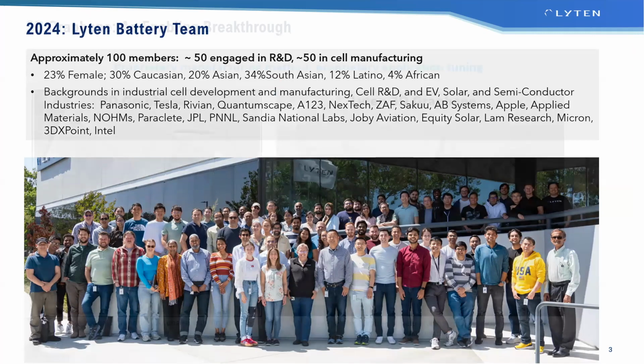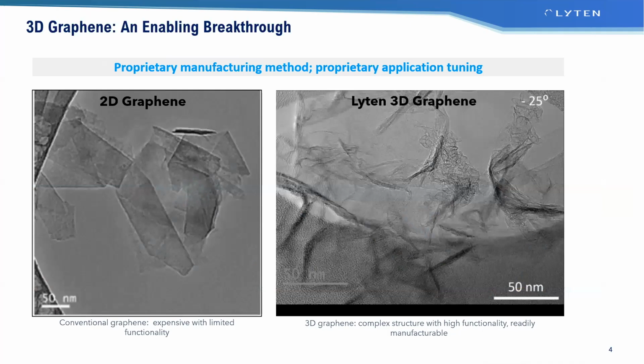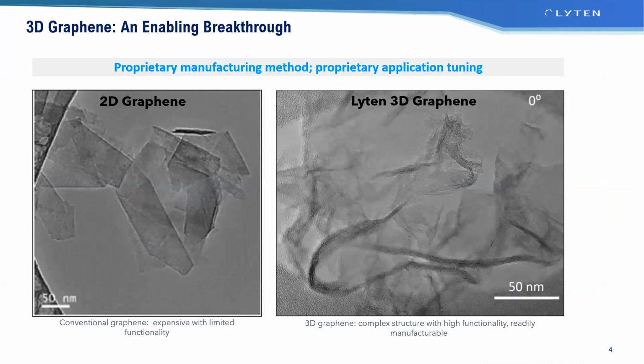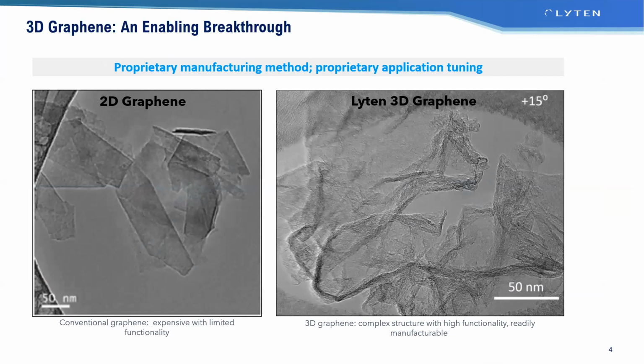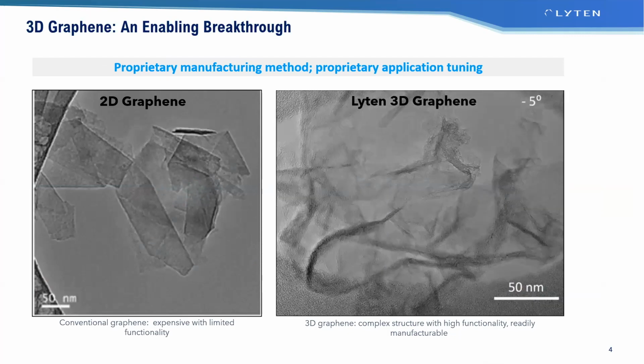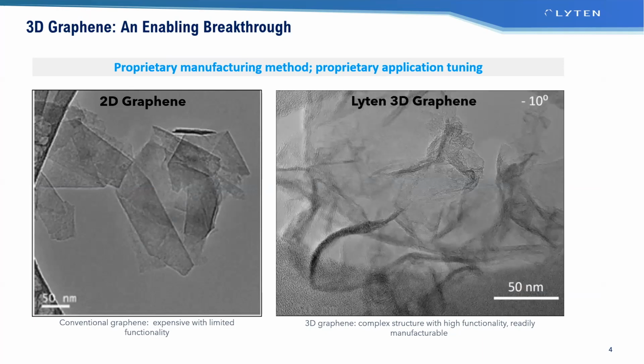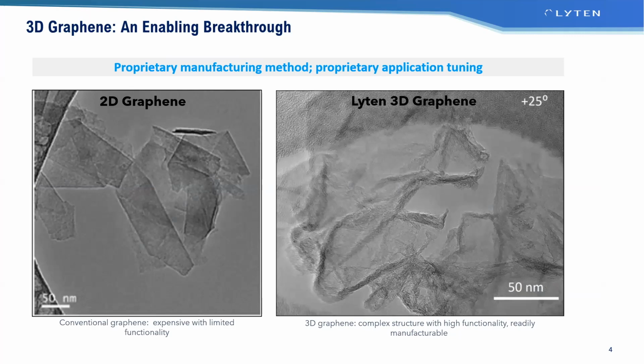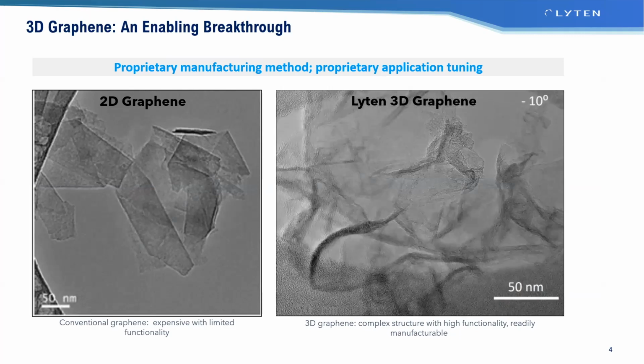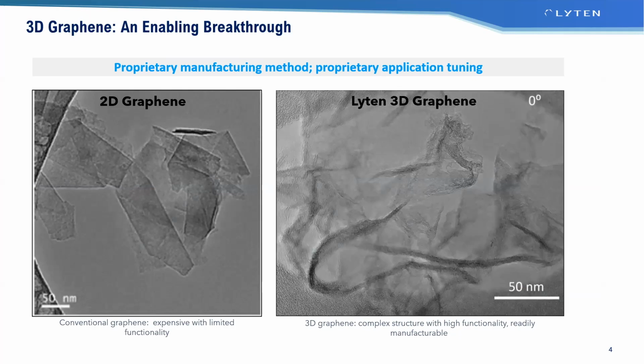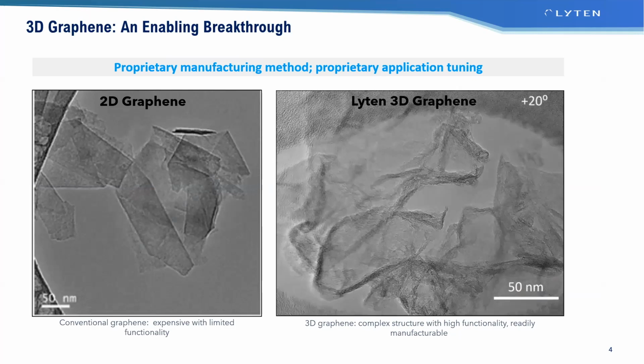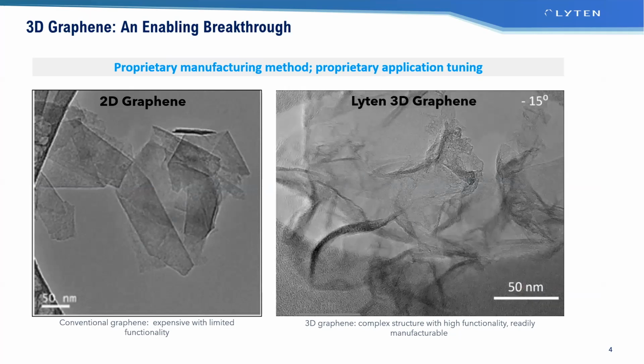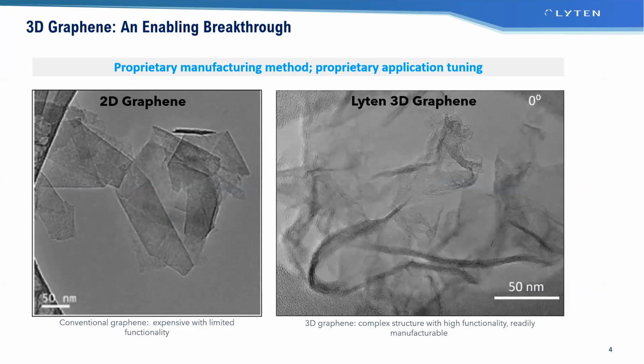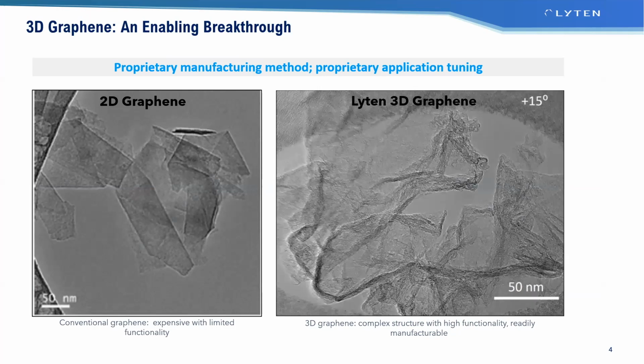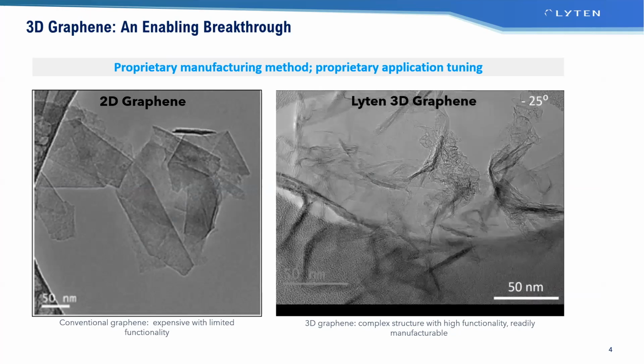So what's the carbon and the graphene we make? Well, graphene itself is the perfect form of plates of carbon, right? All the carbons are bonded beautifully, 6-membered rings. They're resonantly stabilized. The carbons don't really want to do anything with any other molecule around there because they are very lovely, very happy in their bonding structure. But if you make it imperfect, so you add wrinkles and bends and you make something that looks here like a little bit of a mess, because these are carbon layers and they've got bends and twists to them. Well, then it gets more interesting because every bend and twist means you have a 5-membered ring instead of a 6-membered ring in the structure. And that is not a perfectly resonantly stabilized structure.